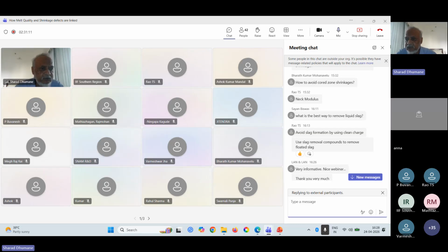Liquid slag is formed when there is a holding, when there is a metal which is exposed at high temperature to air, and then the liquid metal immediately reacts with the oxygen in the air, and liquid slag is formed. So when there is a holding, if we have covered our liquid metal sufficiently, with a furnace cover on top. Some of the foundries do that. When the metal is getting poured and you are waiting for the ladle to come back, they will cover the furnace. In that way, they avoid interaction of the liquid surface with the air.